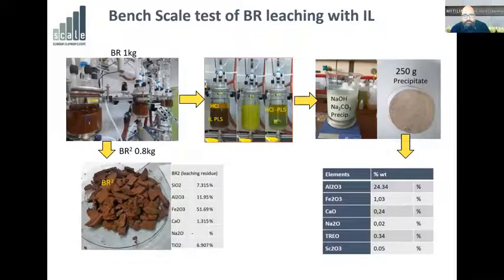And you can see some more details on this method. You can see the bauxite residue being leached with a mixture of water and ionic liquid. Then you can see the collected pregnant solution in the ionic phase. On top of that, we add some concentrated hydrochloric acid, mix it, and you see now you have the regeneration of the ionic liquid and the hydrochloric acid, which now has also much of the water content from the ionic phase. So this specific ionic phase has this miscible and immiscible switch behavior that allows it to be mixable with water at certain pH and temperatures, and non-mixable with water at others.